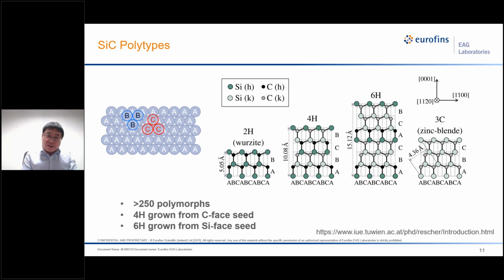So first, let's look at the silicon carbide structures. Silicon carbide is a compound semiconductor composed of 50% silicon and 50% carbon. It has more than 250 polytypes due to different stacking sequence of silicon carbon bilayers along the C-axis of hexagonal close-packed system. So here are the most common structures. The number here indicates the number of silicon carbide bilayers in each unit cell.